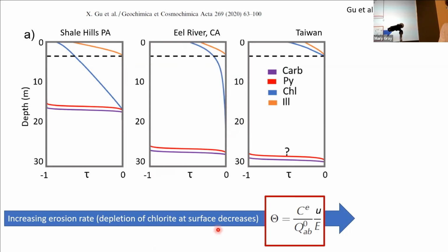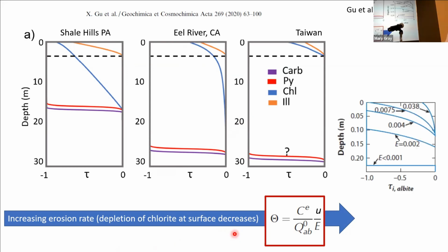And this is what I told you way back in the beginning, the chemical depletion fraction. You expect, for a very slow erosion rate, you can get a very thin reaction front, but as your erosion rate goes up, you're going to eventually expose your reacting mineral. And that's exactly what you see in these chlorite fronts. So this just shows you, I think, a little bit that what we're talking about is happening all around the world. We just need to be able to understand it better and kind of unravel it.